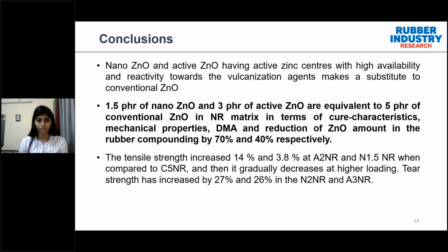So when we look into the mechanical properties like tensile strength or elongation, we can see the tensile strength has increased by 14% and 3.8% for the A2NR and the 1.5 NR when compared to C5NR. And then it gradually decreases at a higher loading, which we explained with the morphological analysis, that at a higher loading the agglomeration is happening. For the tear strength, it has increased by 27 and 26% for the N2NR and A3NR.